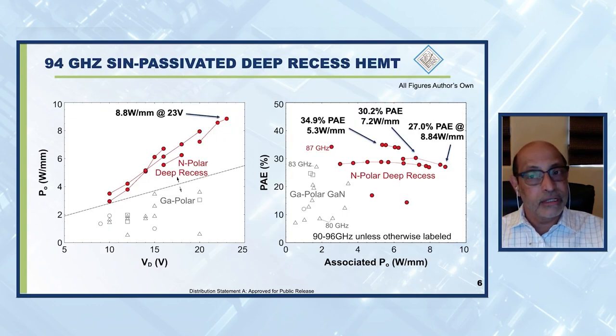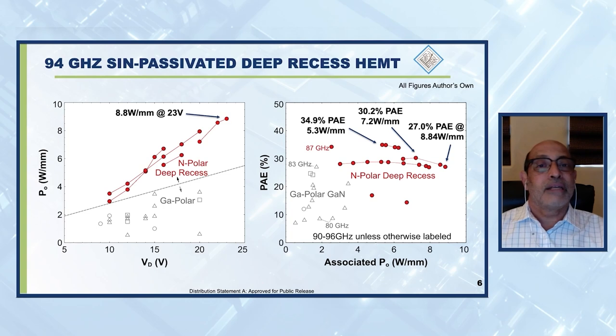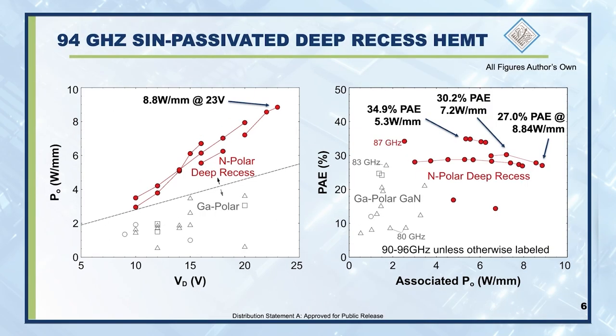At 94 gigahertz, silicon nitride passivated deep recess HEMTs actually end up with an output power density, as a function of bias, that goes up linearly. This linear relationship of power density with bias shows that the device is actually behaving in a near ideal fashion. At 23 volts bias, we get 8.8 watts per millimeter, which a few years ago would have been assumed to be impossible.